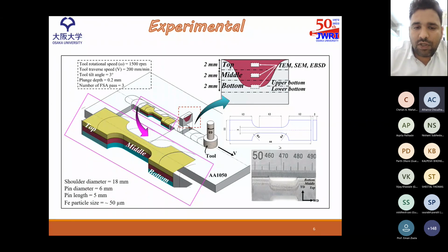This is the schematic of the through thickness experiment. This is a base plate, aluminum, and this is a groove where we have filled the iron powder. And this is a tool, a non-consumable tool. It has linear as well as rotational motion, and it is moving over the groove filled with iron. And this is the formed zone, the alloyed zone. We extracted the samples from the stir zone and further sliced the sample into three parts, that is top, middle and bottom layer. You can see the cross-sectional schematic here.